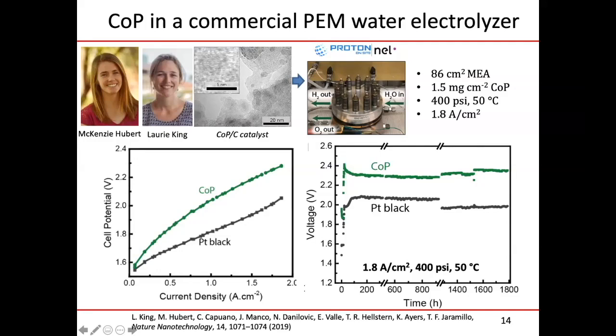And lo and behold, the polarization curves show that yes, when you have a non-precious metal catalyst, in this case, it's a cobalt phosphide based system, you do pay again the 200 millivolt penalty. That's exactly what we would expect it to do for the reasons I mentioned earlier. Nevertheless, it was able to hit the performance metrics that they were after.